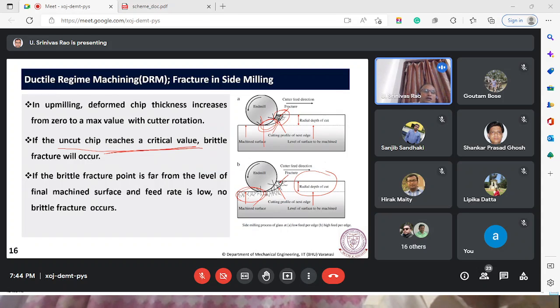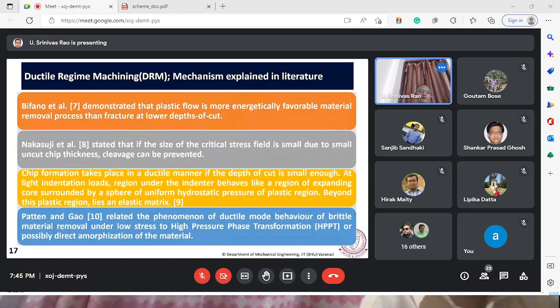So if we can keep the brittle fracture point far from the level of final machine surface, then feed rate is low, then no brittle fracture will occur and we can avoid these micro cracks on the surface. Surface gets formed, but it is having micro cracks on the surface.